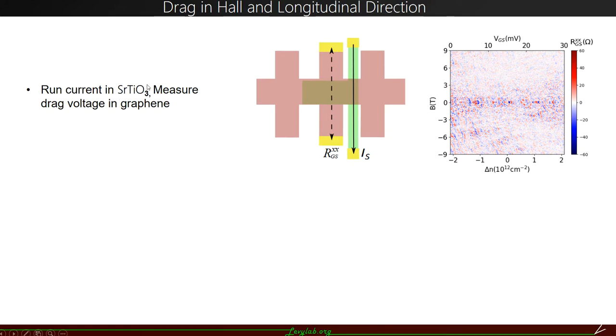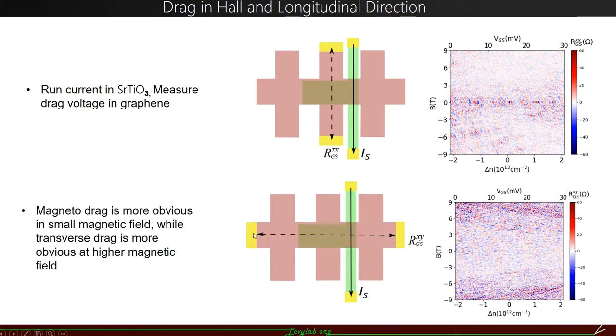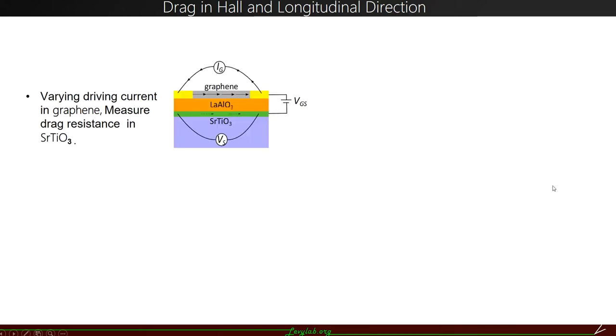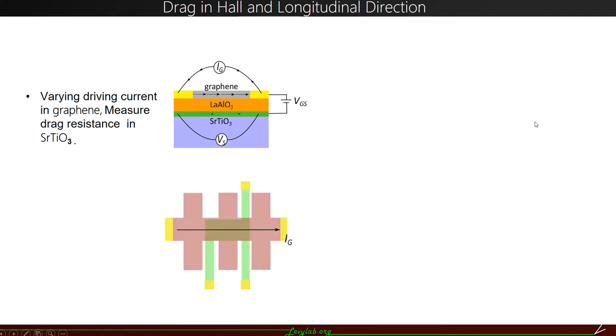We also studied the Coulomb drag in Hall and longitudinal direction. So here we run the current in SrTiO and measure the drag voltage in graphene. If the drag voltage is measured parallel to the driving current, the drag signal is more obvious in the low magnetic field region, and if the drag signal is measured perpendicular to the current, we can see the drag signal is more obvious in a high magnetic field region. And this is also true if we change the current.